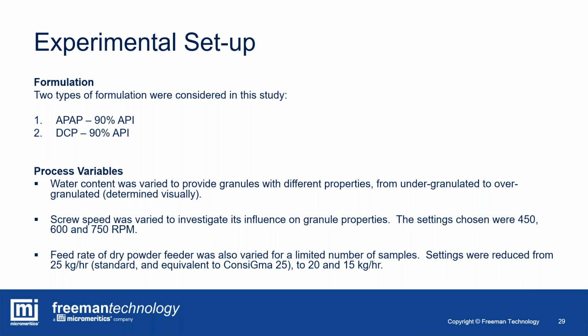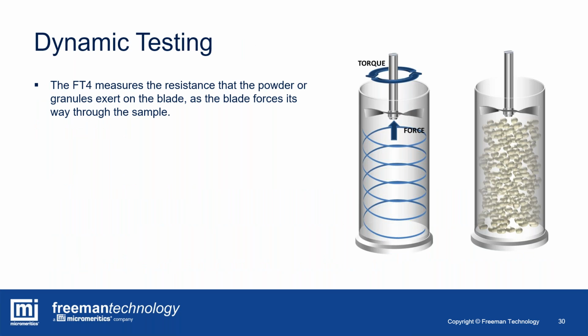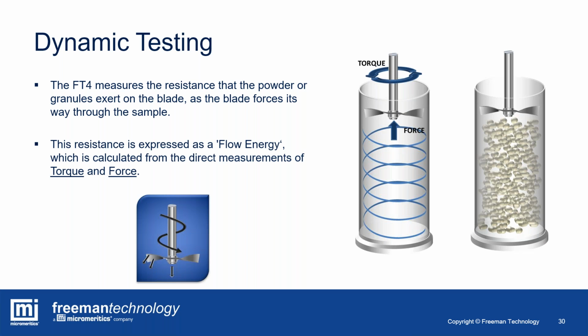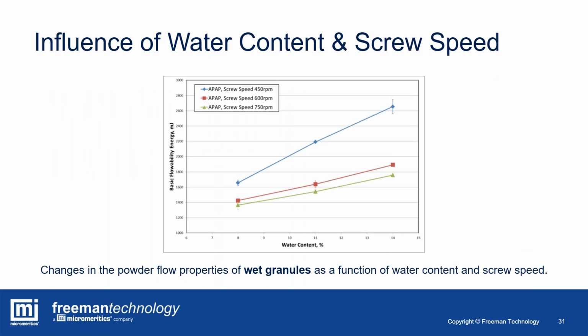So again, we used dynamic characterization. This is the FT4 measuring the resistance of the powder, or in this case, the granules, that they exert on the blade as it forces its way through the sample. And we know that that resistance is expressed as a flow energy, so the calculated resistance measured directly from that force and the torque. So what you can see in this data set is the flow energy measured on the y-axis, and then you have on the x-axis the water content.